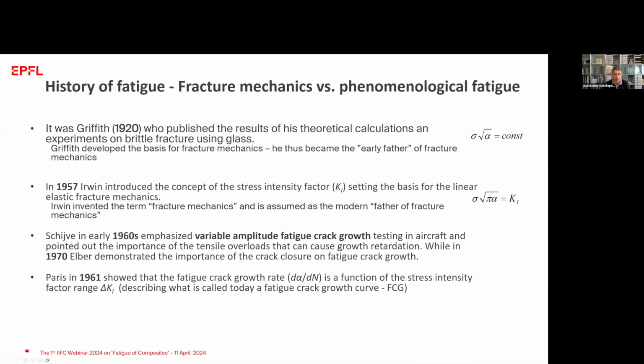And when we talk about fatigue, we talk about Schijve, if I say it well, a Dutch professor, and Paris, where they both worked on what we call today the fatigue crack growth curve. So a curve that shows the relationship between the speed of the crack and the load that we apply. The load can be given by using K or by using G. We use G, the strain energy release rate, for composites. But there is anyway a component that shows the load that we apply, and on the other axis we have the speed of the crack, this dA over dN.